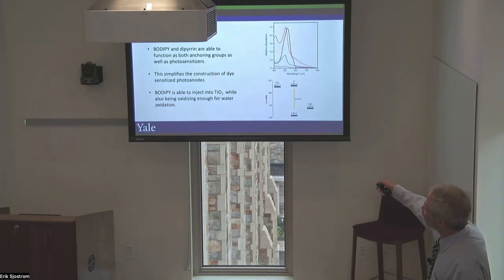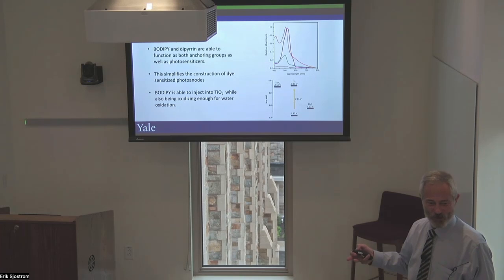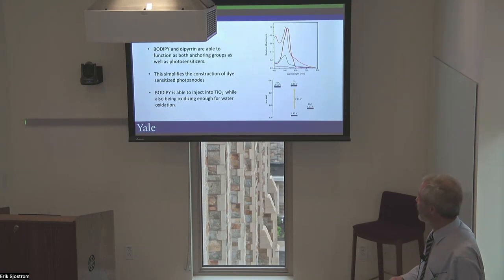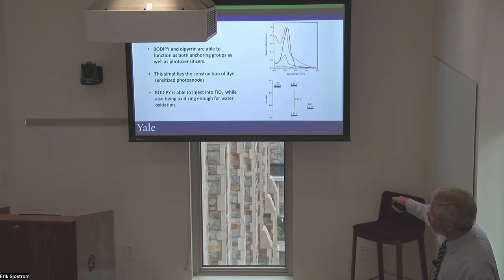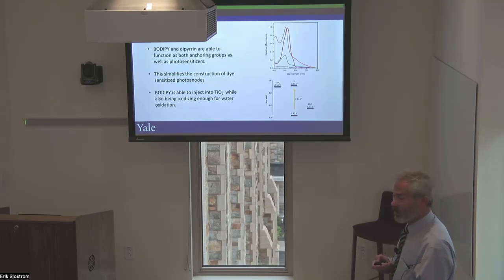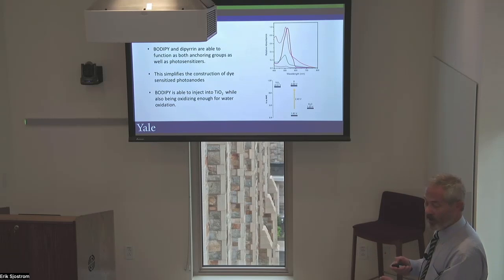And just to summarize, we see that these new molecules, BODIPY and dipyrrin, are able to function both as anchoring groups and photosensitizers. So we kill two birds with one stone by making this. We've got both attachment to the surface and also visible light absorption, which simplifies the construction of these dye-sensitized photoanodes. And it's able to inject on an ultra-fast time scale, but also be oxidizing enough to do water oxidation. So what we're in the process of doing now is coupling this new anchoring group and dye combination with a water oxidation catalyst to do light-driven water oxidation. And that's in progress. So hopefully we'll have something to talk about the next time around.